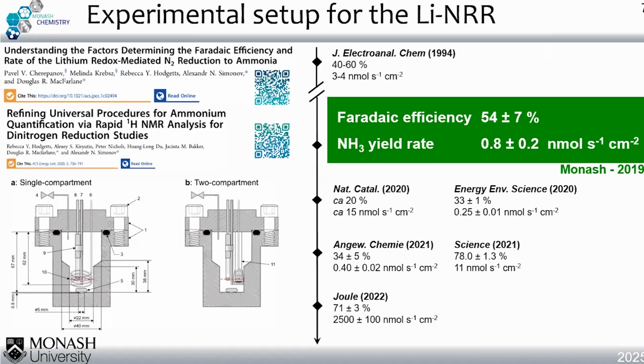Then until 2019, we revisited it and tried to understand the concept. We reproduced the results. After that, we can see that many research groups got involved, and they tried to develop the performance. The rate has improved, but if you focus on the Faradaic efficiency, it's not 100%. And this is very critical to reach 100% Faradaic efficiency because it is related to maximizing the energy efficiency.